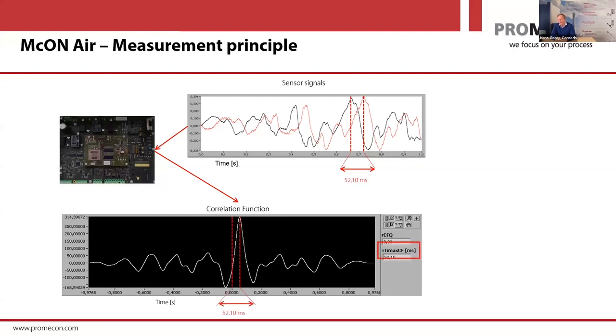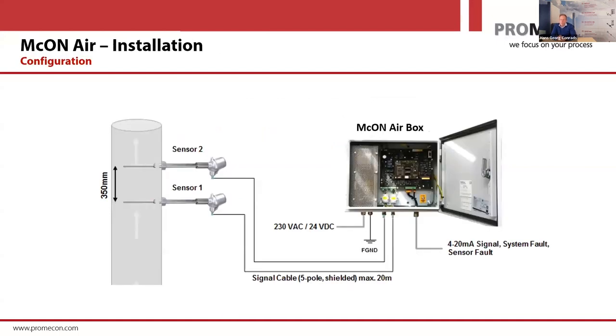So in this case here, that means 52 milliseconds is the time shift. And with the distance of the sensor and the time shift, you can calculate the gas velocity. And using the temperature, you can then calculate the gas flow, including the gas enthalpy flow. So this is how the box looks. You have two sensors, you have our electronics, and out comes a 4 to 20 milliamp signal, or a digital signal if that's preferred, that gives you the gas flow. What I mentioned also is that we can measure temperature of the gas at the same time. So it's easy to measure the gas enthalpy flow and also the energy flow, the thermal energy flow of the gas.